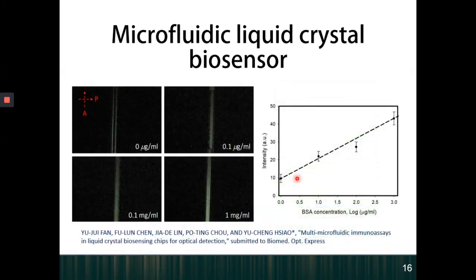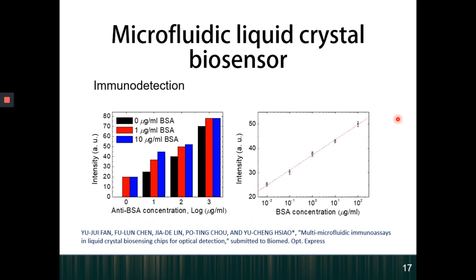We also plotted the intensities against the concentration of BSA in log form, and you can observe that as the BSA concentration increases, its intensity increases. We also did some immune detection here, and it got the same optical behavior. So based on this research, liquid crystal can be applied for these microfluidic applications.